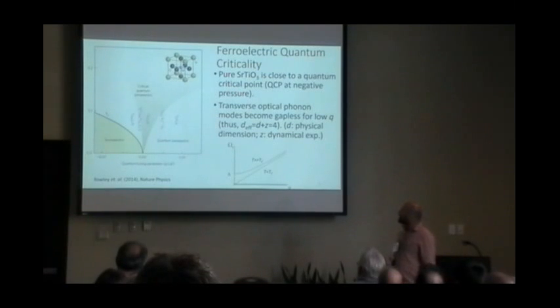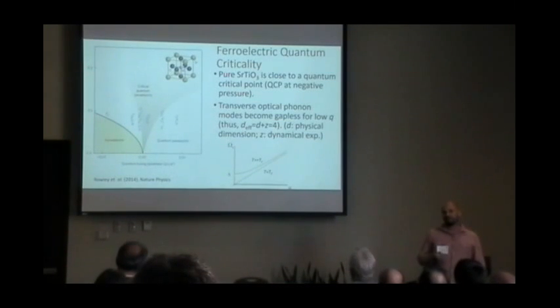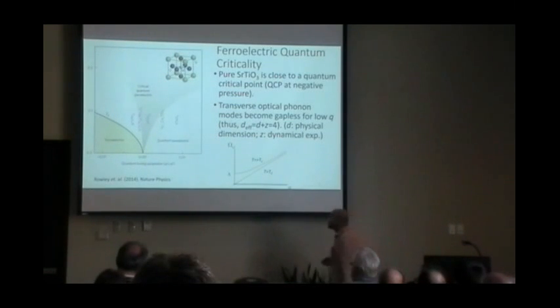So one of the properties which is actually responsible for strontium titanate being so interesting is that it has a ferroelectric quantum critical point at negative pressures. So if this can be done experimentally, so if you substitute the oxygen with an isotope, then you can tune to